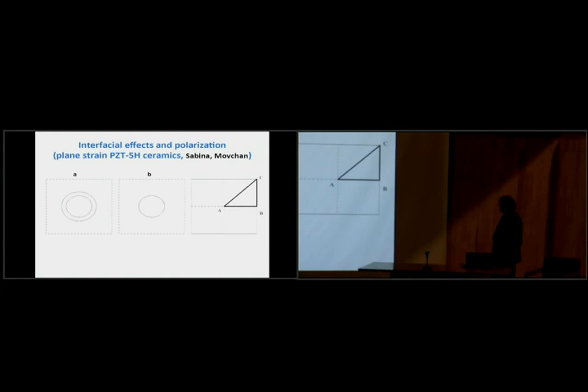So, in this case, if you choose a two-dimensional structure now, and this will be a square, doubly periodic composite, and here you see the elementary cell, and what you will do is you have two types of materials, and then you can either introduce a thin interface, which may have just different properties, like very different stiffness, or you can play with the polarization. And piezoelectric materials allow you to do it. So in principle, you can have identical material in terms of elastic properties, but different polarization inside and outside, and this will create an effect.